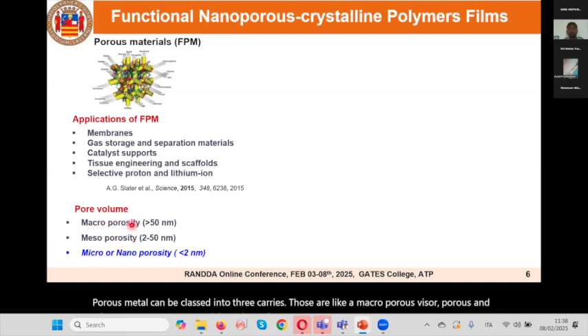If the material has pores larger than 50 nanometers, those materials are considered macroporous. The second one, mesoporous, has pores between 2 and 50 nanometers. And the third one, micro or nanoporous, has pores less than 2 nanometers. These kinds of materials come under microporous material. So coming to our question, among the three systems, the microporous material has a very small pore size. Due to the small pore size, they have high selectivity in molecular sensing and many other applications. Due to this high selectivity, nano or microporous materials are of fundamental interest.